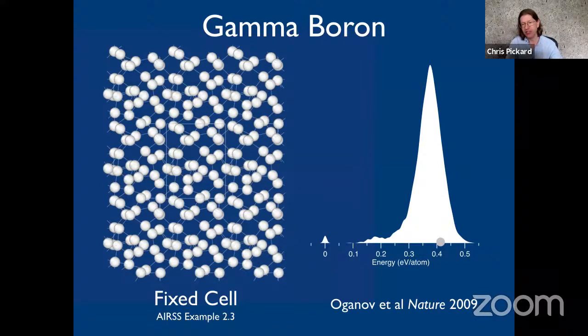What I show here on the right-hand side is the density of structure states. So what I do is I do many, many simulations and I make a density of states, like the electronic density of states, but for the energies of the structures. And the peak at the bottom is the ground state at zero. And then you have these higher energy states and the big high peak is the sort of glassy or liquid-like state at higher energies. You can see there's a lot more weight in that glassy or amorphous state and lower in the ground state. Somewhat obviously, there's many more ways to be messed up than there are to be in the right arrangement.